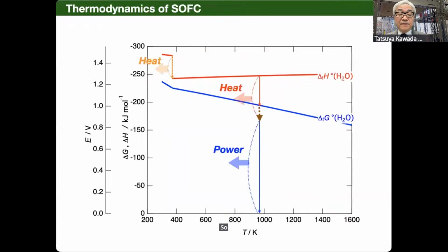So this was the power generation. But if you use it as an electrolyzer, the situation is also better, because in electrolysis, the power you need to decompose water to hydrogen is less than the enthalpy change of water formation. That means if you have an external heat source and you can use that heat, then the enthalpy to power ratio can go higher than 100%. So this cannot be achieved by low temperature systems.